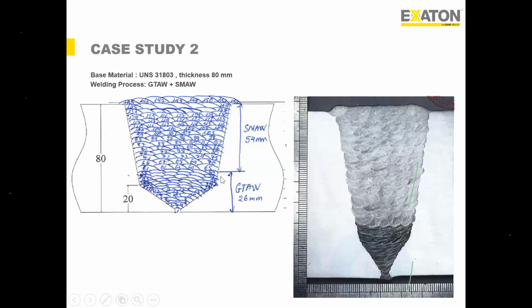Yeah, Sukhmal, just out of curiosity, what was the groove angle at the bottom and at the top? Yeah, so this is another thing. It was basically 80 millimeter thick. So here on the bottom, the groove angle was around 70 degrees, but the more we go up, as you can imagine, it was quite wider. So here we try to make it around 35. 35 on one side or included 35? The included was 35, just to make it narrower. Okay, fine.